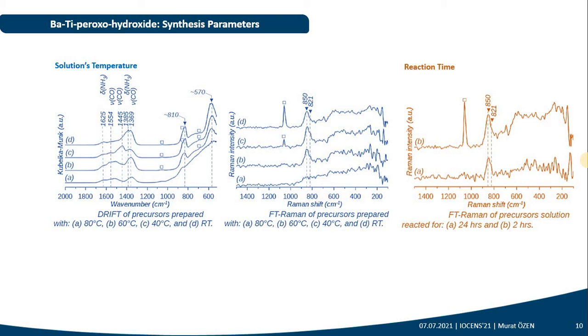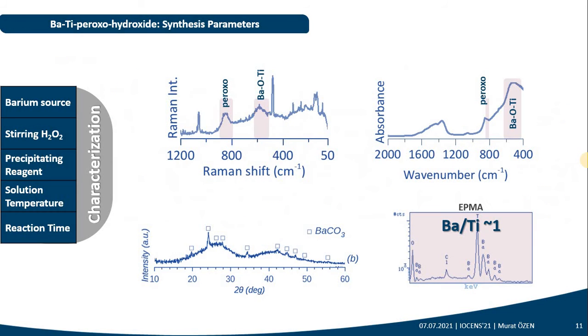Instead of going through all of these results, which will be very exhaustive, I will be summarizing the main results here. The different characterization methods that were used, as I said, were Raman, infrared, XRD, and EPMA analysis, which is an elemental analysis method. In Raman, we will be looking at specific peaks or bands above 800 cm⁻¹ and around 600. In IR, we will be looking at bands at about 800 cm⁻¹ and about 600 cm⁻¹.